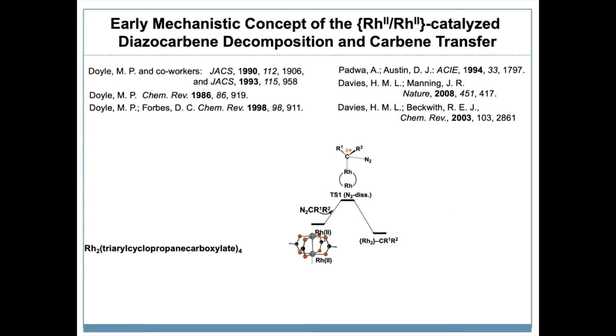That's just simple information. It is also known that chemists use different types of catalysts for diazo compound activation, decomposition, and carbene formation. Diazo activation is really the extrusion of N2 and making the carbene complex, and people use this extensively in the literature. It's a dirhodium tetracarboxylate type of species, or there are simple copper or iron catalysts for these purposes. There are many different catalysts, but the rhodium catalyst, which we mostly concentrate on, is very selective, and we can do selective, high-yield reactions. For example, this is one of the rhodium catalysts my collaborator is working on. You can reach 6 million turnover numbers. It is huge, even though rhodium is expensive. You can use 0.00-something percent and carry out these reactions.